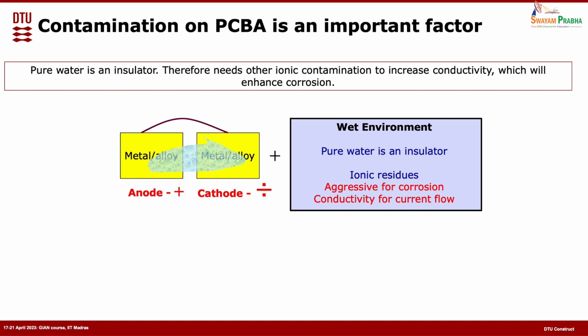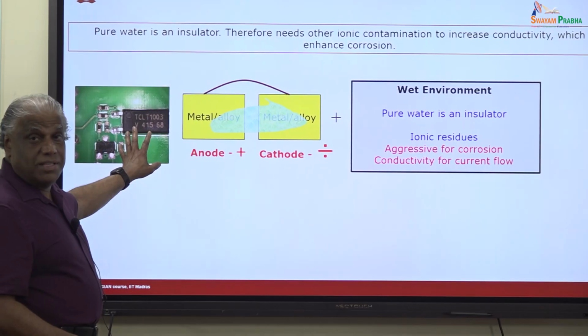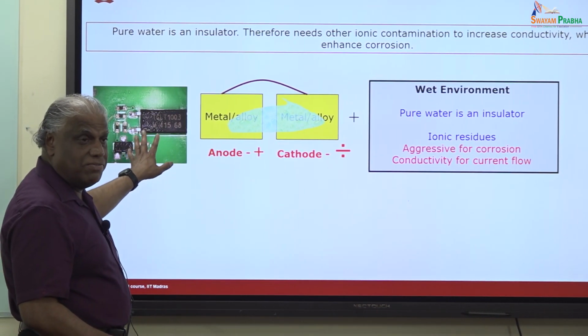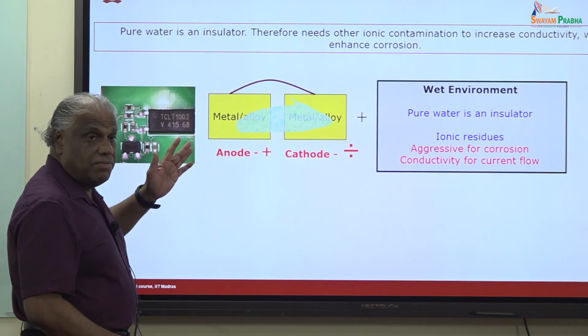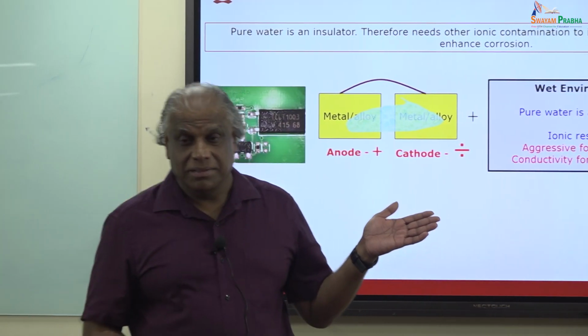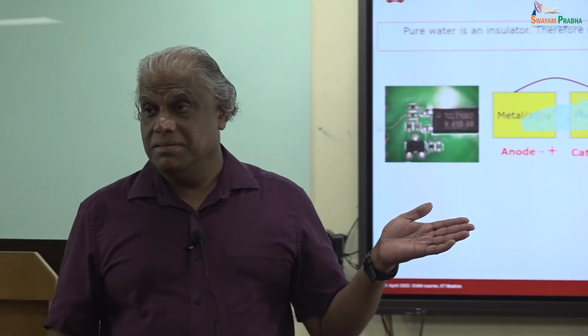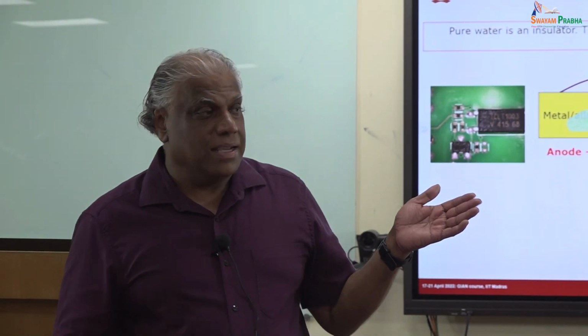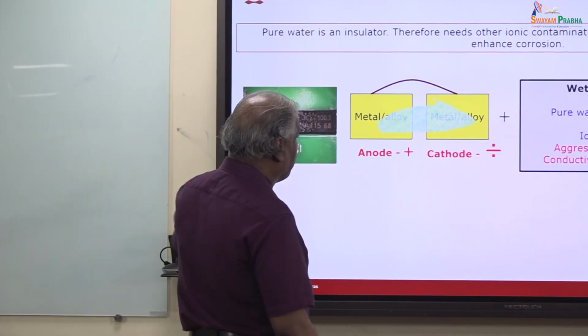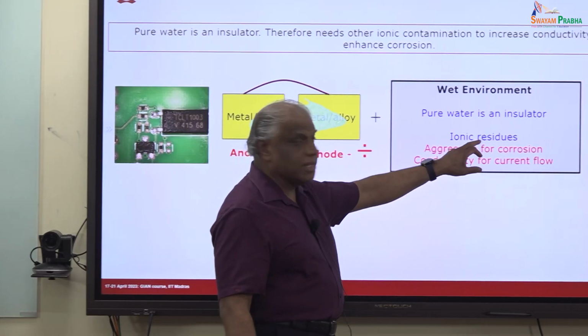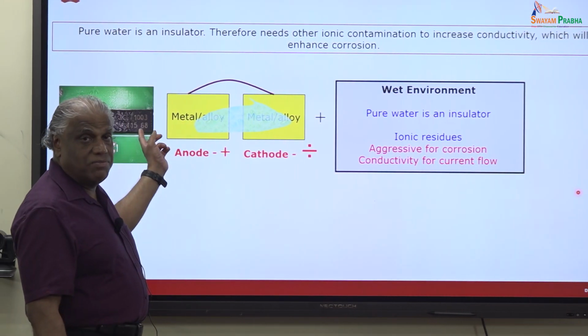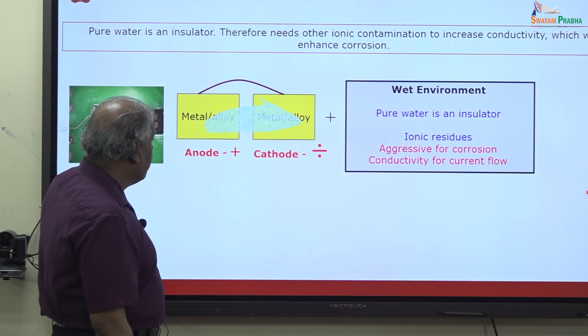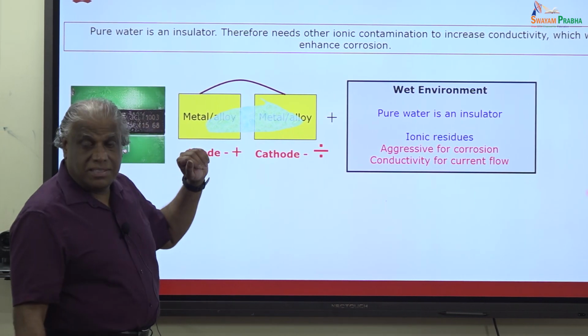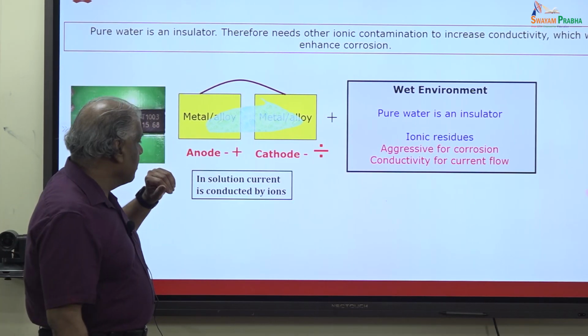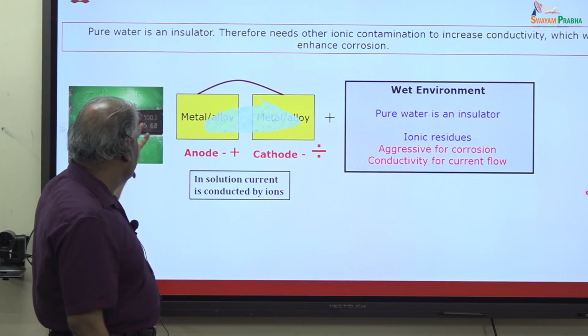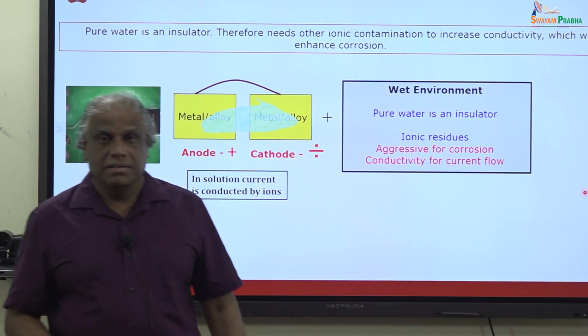Now, when you take an electrolyte, you need some conductivity for the electrolyte. The pure condensed water film is more of a resistor, right? What is the resistance of pure water? Around 10 to the power of 8 ohm, right? So you need some conductivity of the water film, and there comes the importance of the ionic residues on the printed circuit board surface, which come from the manufacturing. When the PCB is manufactured, as I mentioned, they use flux systems to solder. This flux system will leave some residues on the surface, and the residue will be dissolved into the water film, and that is what actually causes